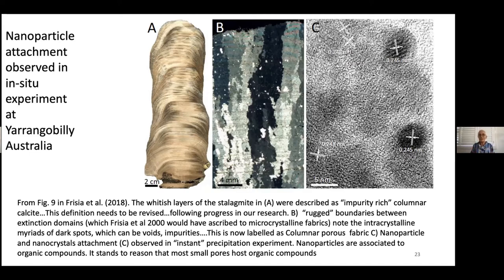It's a different type of fabric. And the boundaries between the crystals are interfingered, are strange. I used to call it columnar microcrystalline. The problem why I dropped the microcrystalline is that I didn't look at these specific fabrics with the transmission electron microscope. So I don't know if they are full of dislocations, but that's part of the evolving story of fabrics. So let's call it columnar porous.